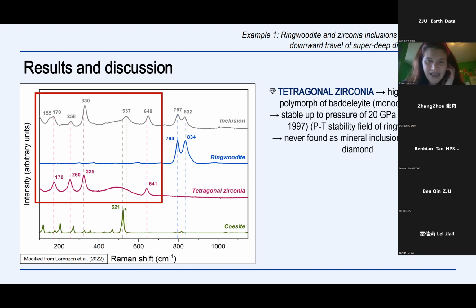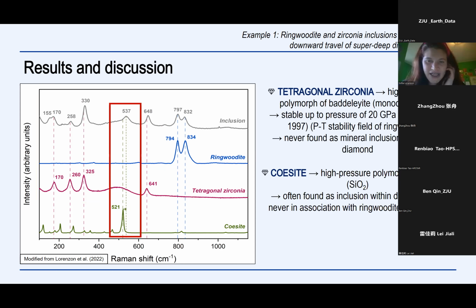Finally, we found coesite in association with these two mineral phases. Coesite, as probably all of you know, is the high-pressure polymorph of quartz. Even if coesite is an extremely common mineral inclusion within diamonds, this is the first time that coesite has been found in association with ringwoodite and tetragonal zirconia.